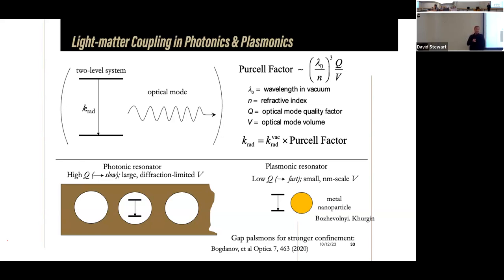And what if you would go the other way? So basically, I still need to increase the coupling, but let's keep Q modest, like in the case of plasmonics. Typical Q for plasmonic structures, such as these gap plasmons or the nanoantenna plasmon, is 100. The carrying frequency is 10 to the 15. If quality factor is 100, it means that the width would be like 10 terahertz or so. It means that the response time would be like 100 femtosecond. So it would be very fast.